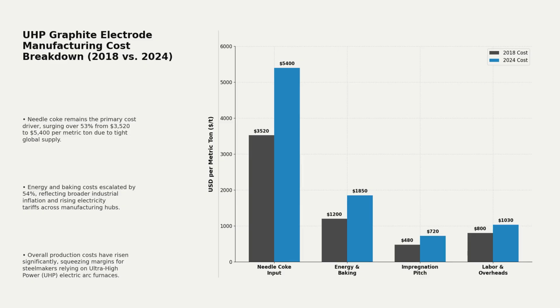Manufacturing 1 metric ton of finished ultra-high power electrode requires approximately 1.2 tons of needle coke due to material loss during high-temperature baking. This high consumption ratio makes electrode pricing extremely sensitive to raw material volatility. Between 2018 and 2024, the total manufacturing cost of these electrodes rose 50%, reaching $9,000 per metric ton. Needle coke inputs alone now account for $5,400 of that total. Compounding this, energy and baking costs rose 54.2% over the same period, threatening the operating margins of electric arc furnaces.